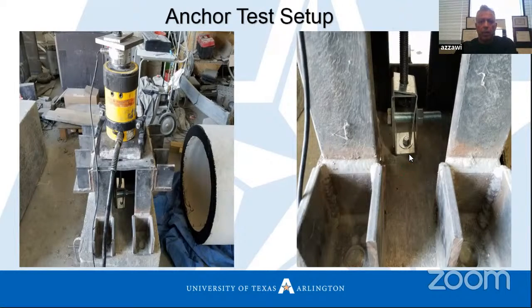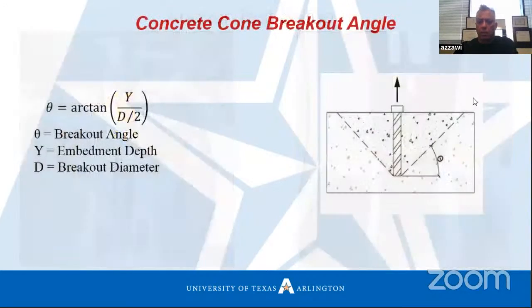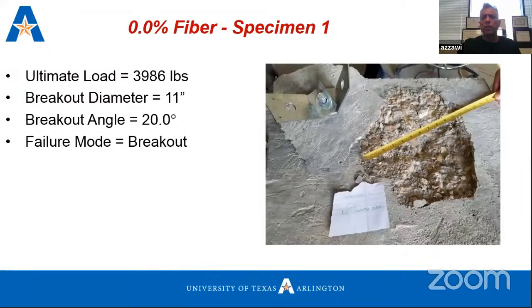Then we start applying tension to these bolts, and you will see how much tensile strength they can carry, what the type of failure is, how much the concrete cone diameter is, and how much the concrete cone breakout angle is. A larger angle means more strength, more capability to resist, more tensile strength. We tested 5 specimens for each mix design.